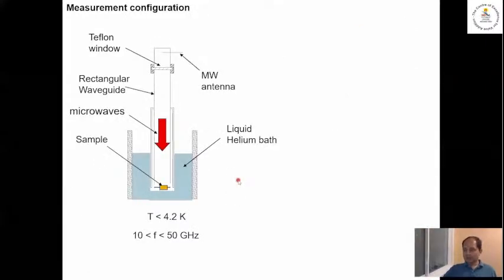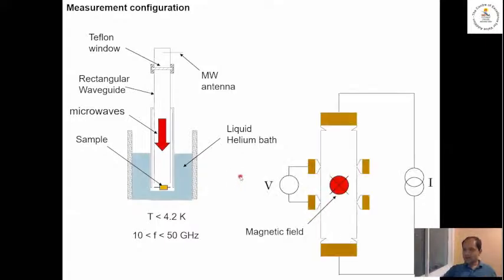So what do we do with this? We take this epitaxial graphene, we make a device with electrical contacts. Device looks like this. It's a Hall bar, where these gold areas are electrical contacts. And then what we do is we pass a current through the device, and then we measure the voltage across some contacts in a 4-terminal configuration. And then the resistance that we report is the voltage divided by the current.